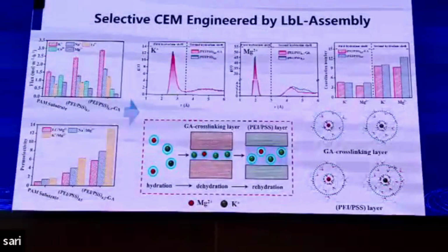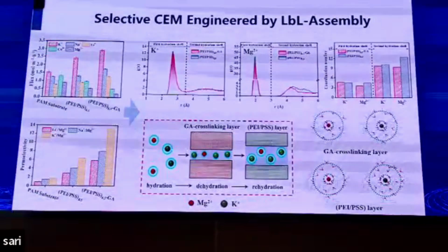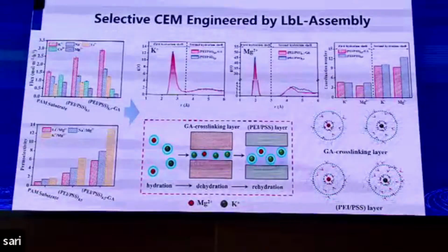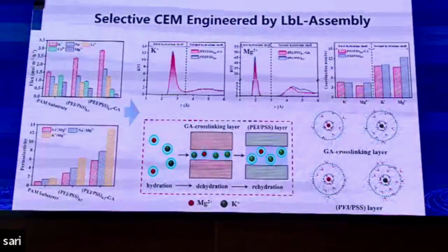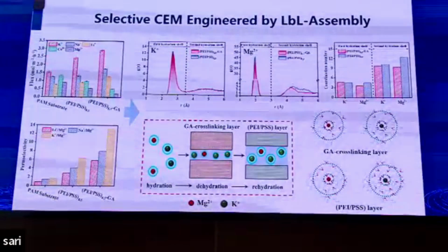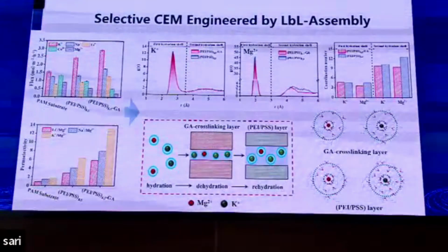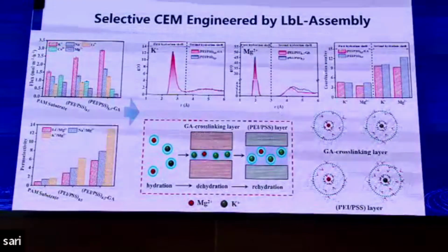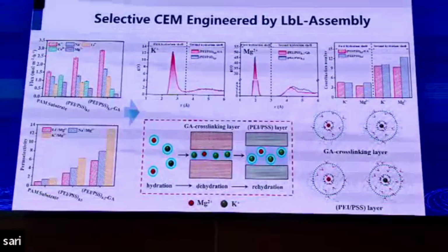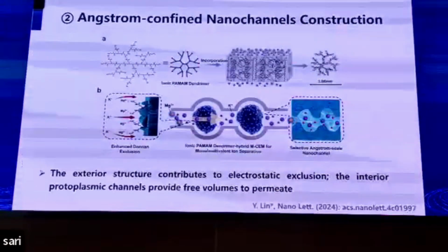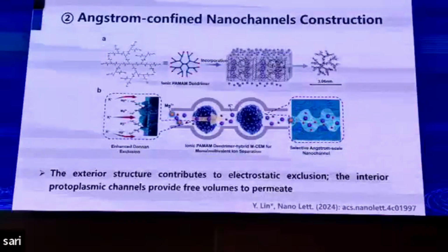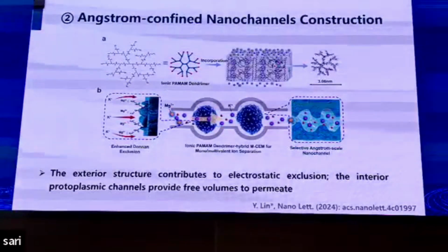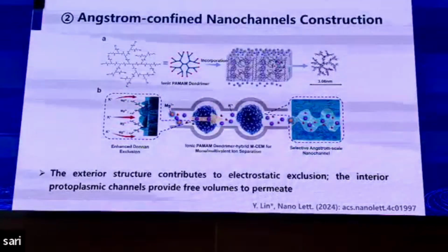Obviously, we can say that for these pore channels, when divalent ions get inside, they suffer higher energies to strip their outer hydration layers, so they must overcome a higher energy to permeate through. It's a steric hindrance that prevents their permeation. And after that, we thought, yes, the pore channels decreased, but the resistance increased. So it's not so good for making highly efficient membranes.